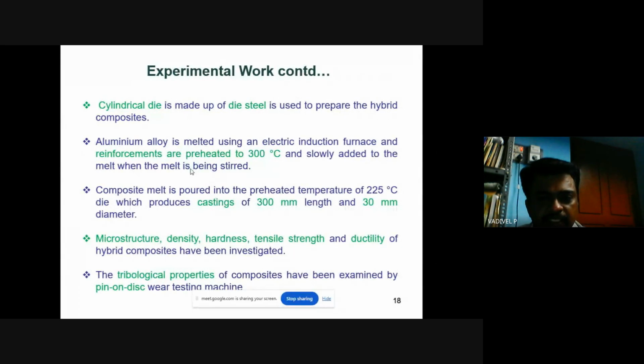The aluminum alloy is melted in the furnace, and the reinforcements are preheated to 300 degrees Celsius. The preheating of reinforcement is very important, because if the matrix aluminum metal is at a very hot temperature and the reinforcement is not preheated, the bonding between the aluminum material and the reinforcement is not good. In the first two and three trial experiments, preheating was not done. At that time we identified that there is no proper bonding between the aluminum and the titanium diboride and boron carbide.